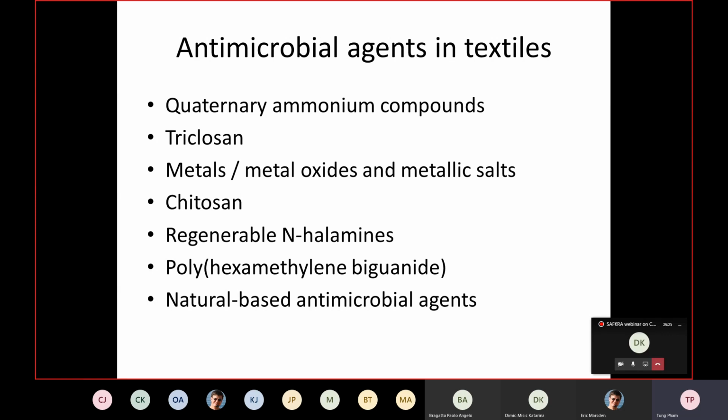The second widely used agent is triclosan, which is an odorless synthetic chlorinated bisphenol, which is not ionized in solutions. This biocide agent mainly acts by blocking lipid biosynthesis. Triclosan is used in many applications, including soaps, lotions, creams, deodorants, and so on. In textile, triclosan is mainly used in polyester, nylon, polypropylene, and acrylic fibers. It raises some big concerns because it may produce certain antibiotic cross-resistant strains.